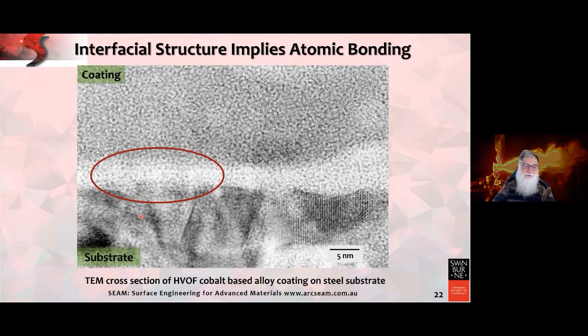If we look very closely at the interface between a substrate and coating, as shown here and in this area I've indicated, you can see some intermingling, almost diffusion controlled or physical impaction of material of the coating into the substrate. Now, traditionally, I would say that there is no chemical profile across the interface. However, recent evidence with new processes, such as cold spray, has shown that there seems to be a physical interaction at atomic scales across the interface. This is also true of HVOF, by the way. But the point that I'm getting to is that the interfacial structure refers to the atomic bonding and hence adhesion.